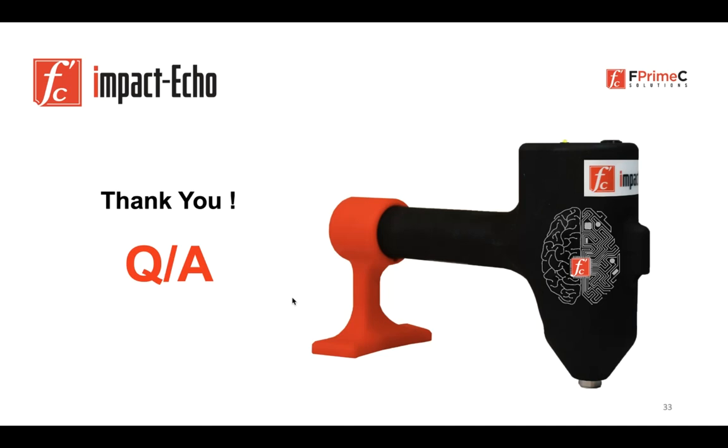If you are doing the impact echo, complete those tests with UPV as well, or maybe if possible, take just a few number of the cores just to make sure whatever you are talking about based on your impact echo test and you are going to reject the concrete, the cores as well show the same things, because that situation is very difficult and you need to convince a lot of people after a lot of investment. The job you are doing is poor and very bad. But for accepting, yes, you can use your impact echo. If the results are adequate and satisfying, you can say the concrete is good and you can tell the contractor to proceed with the next stage.